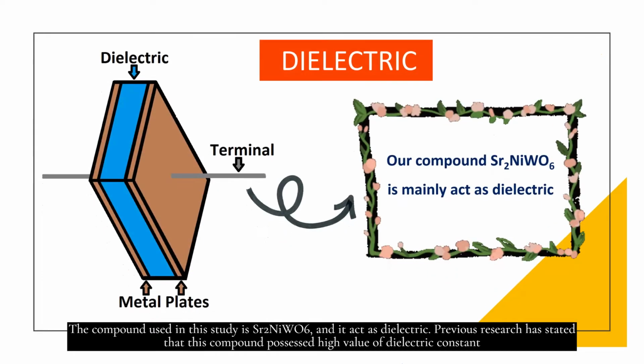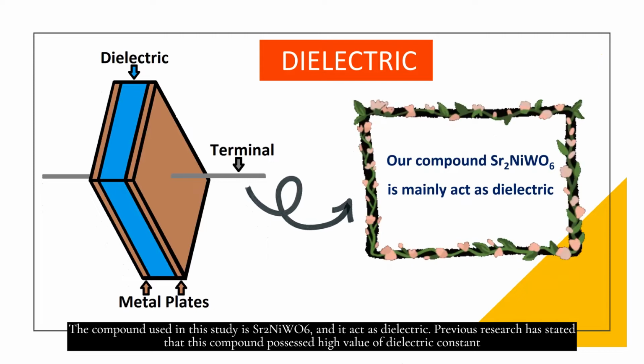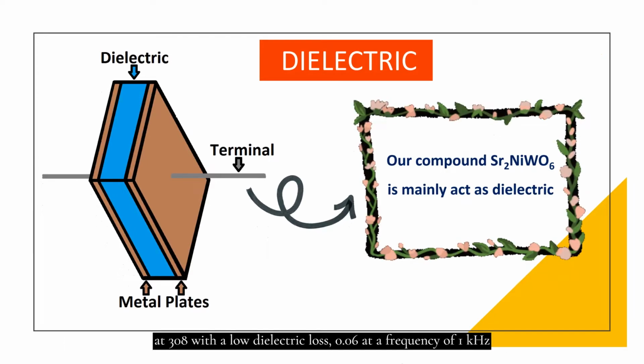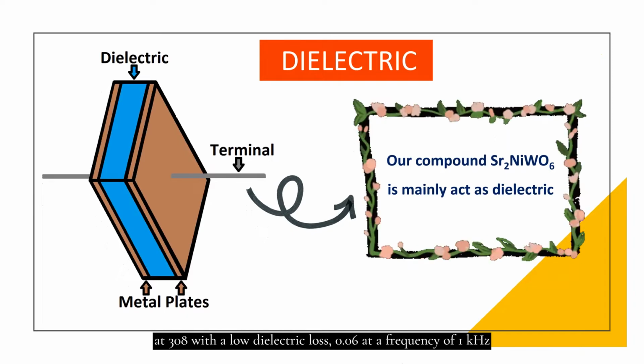The compound used in this study is Sr2NiWO6, and it acts as a dielectric. Previous research has stated that this compound possessed a high dielectric constant of 308 with a low dielectric loss, 0.06 at a frequency of 1 kHz.